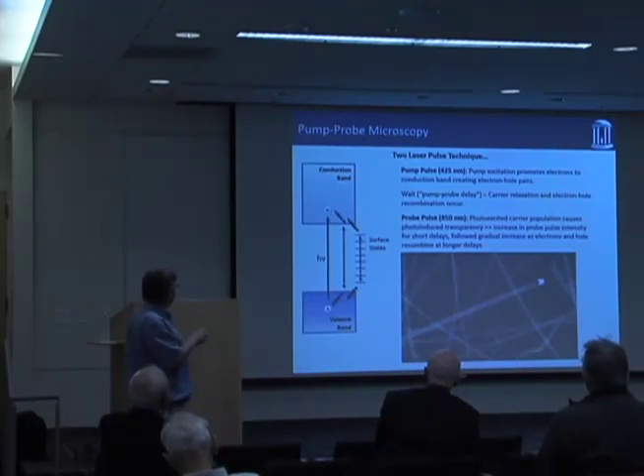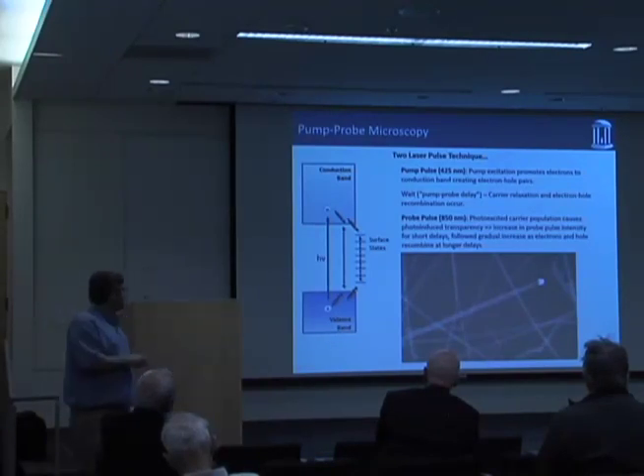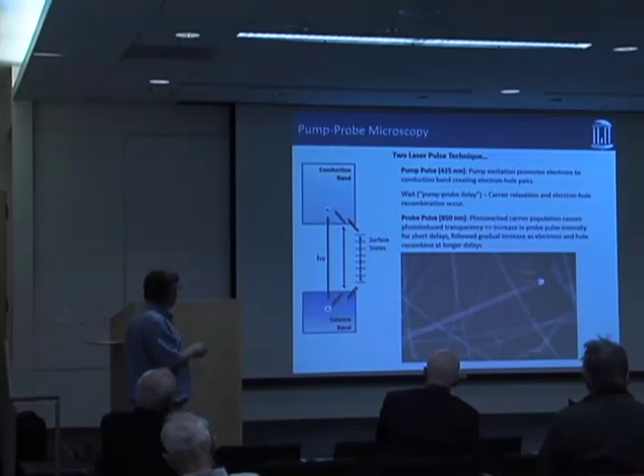It's a two-pulse laser pulse technique. We have a pump pulse that's tuned to 425 nanometers, which is above the band gap of silicon. The beam is going to be focused down to a spot size that's about the size of that circle. So here's a nanowire. That nanowire is probably about 100 nanometers in diameter or so, maybe 150. That thing there is the gold catalyst that was used to grow the nanowire. And so our pump pulse is going to be small compared to the length of the nanowire, but it's going to be large compared to the diameter.